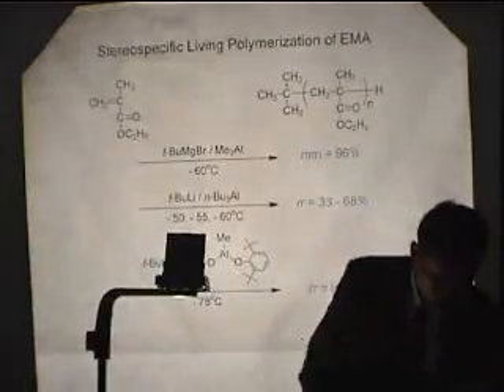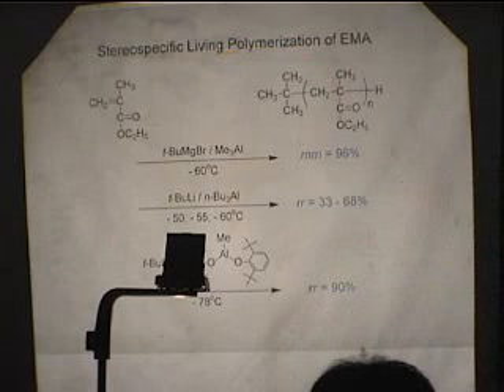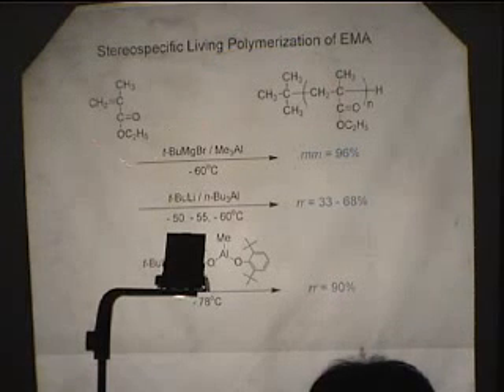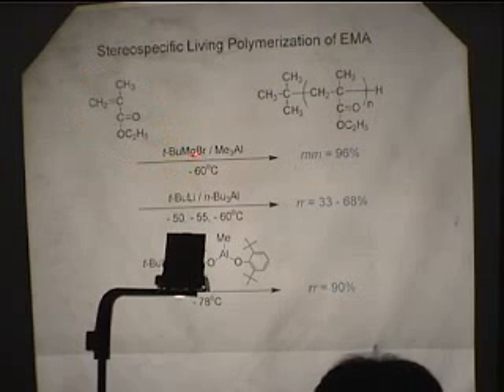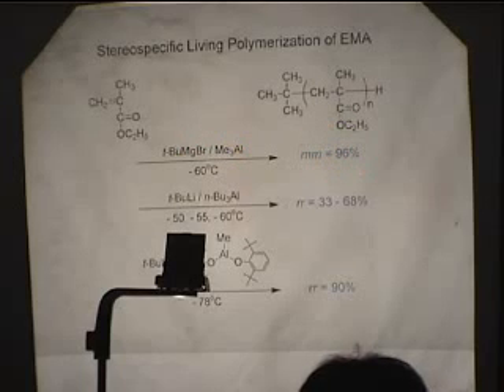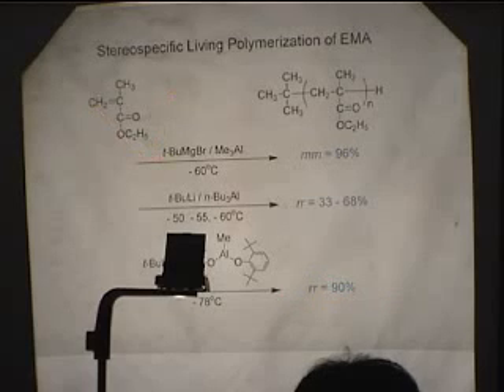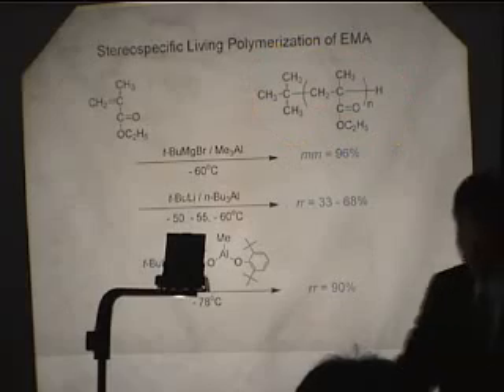Ethyl methacrylate can be polymerized in a living and stereospecific manner. When this monomer was polymerized with tert-butylmagnesium bromide and trimethylaluminum system, a polymer with high isotacticity was prepared. Whereas the polymerization of this monomer with tert-butyllithium in the presence of a bulky Lewis acid gives a polymer with high syndiotacticity. When this monomer is polymerized with t-butyllithium and n-butylaluminum system, polymers with moderate syndiotacticity are prepared. All the polymers have the same chemical structure except for tacticity.